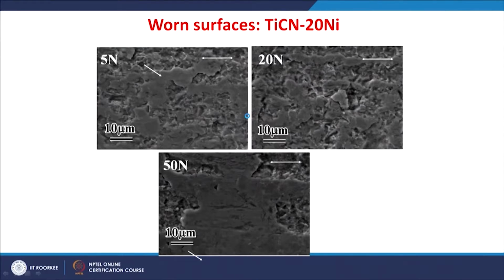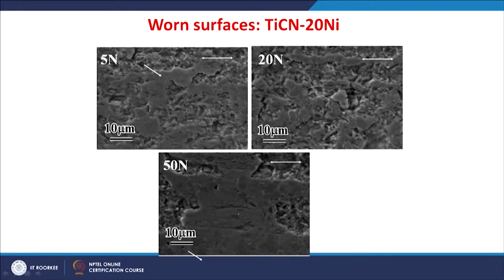Let us understand the behavior with respect to wear and friction by studying the worn surfaces. These are the SEM images obtained for the baseline cermet of titanium carbonitride with nickel at 3 different load conditions. After the wear test was done, these were subjected to SEM analysis, and you can see these surfaces reveal a deformed region and large pullouts at lower load conditions, whereas at higher loads the surface is more or less covered with a layer, and such a layer is minimal at lower load conditions. So, one observation is that at lower loads the wear is dominated by pullout or deformation, and at higher loads it is basically by layer formation and its removal.